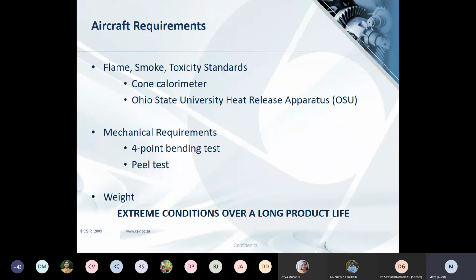Now these are the aircraft requirements, FST standards, and the flammability was measured in two equipments. One is the cone calorimeter and the other one was the Ohio State University heat release apparatus. Now both equipments measure the flammability, mainly the heat release in a material while burning, but the principle of measurement is different. Cone calorimeter is based on oxygen consumption of the sample during burning, while OSU is related to the thermal flux of the sample while burning.